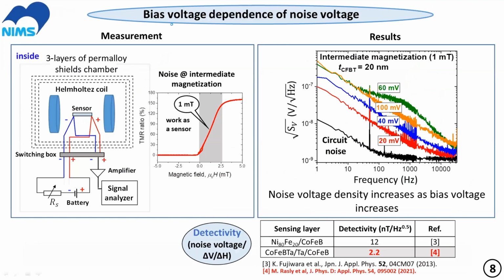After that, we went to the noise measurement. We put our sensor at the center of a Helmholtz coil inside a 3-layer permalloy shielding chamber. We biased our device using a battery box, and then the output signal was amplified before going to the signal analyzer for FFT analysis. And actually, we biased our device by 1 millitesla in order to bring it to the intermediate state of magnetization, where the MTJ works as a magnetic sensor during this region.